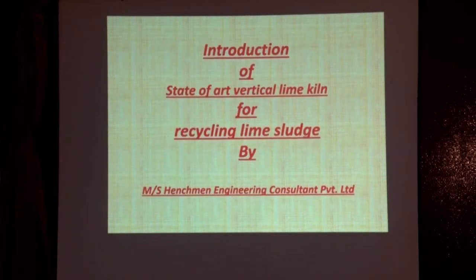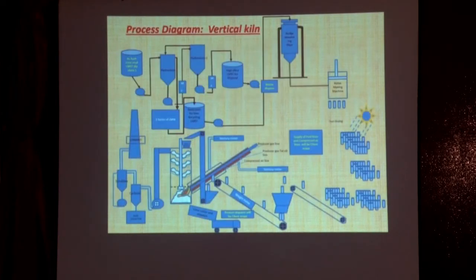This is where the state-of-the-art pellet lime kiln introduction comes in. For the state-of-the-art vertical lime kiln, we thought about why agro-based paper mills cannot run their lime kiln. Why are they so reluctant to run the lime kiln, with CPCB putting pressure on them, because they cannot throw this lime outside the mill because of the high silica content. They are unable to run the rotary lime kiln because their silica content is as high as 5% to even 8%. For the experiment, we took the mud of one of these agro-based paper mills. We cannot disclose the name of the mill, but the silica content was 8%.